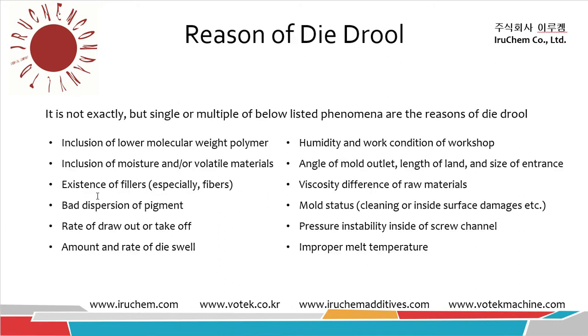It is not exactly known why die build-up occurs, but the following things are suspected to be the main reasons: the inclusion of low molecular weight polymer, the inclusion of moisture and/or volatile materials, existence of fillers — especially fiber-like fillers — bad dispersion of pigment, rate of draw-out or take-off, amount and rate of die swell, and other minor factors.